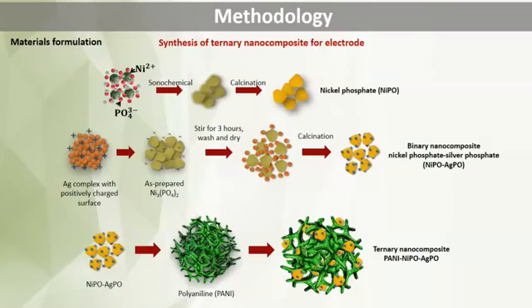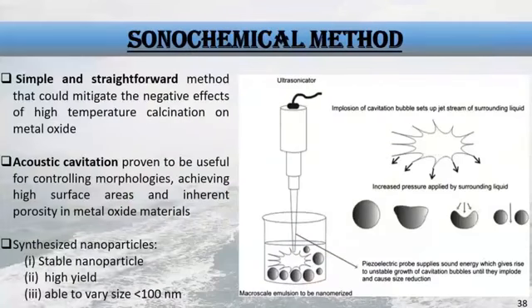So the nickel phosphate can be changed to become a binary nanocomposite by incorporating silver complex with positively charged surface. And the incorporation of polyaniline also can produce the ternary nanocomposite of polyaniline, nickel phosphate, and silver phosphate. And the method that we are using here is a sonochemical method. And this sonochemical method is a simple and straightforward method.